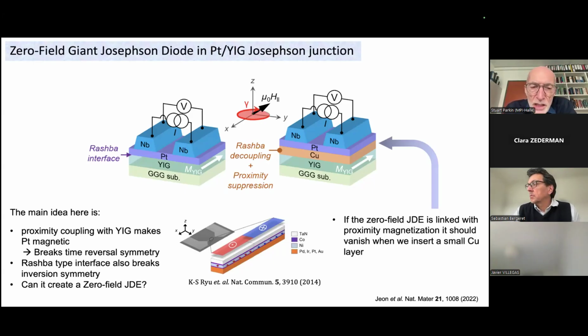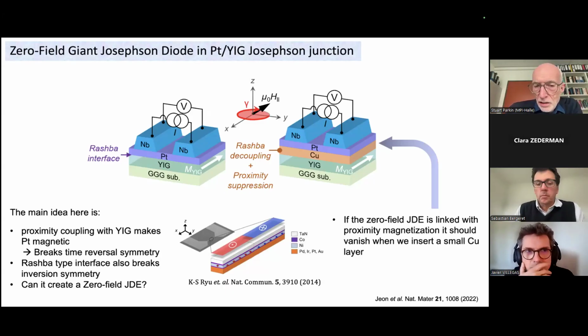In this case, we break time reversal symmetry in platinum by growing a platinum layer on a substrate which is insulating, but which is a ferrimagnet. This is a so-called YIG, a yttrium iron garnet film, and it has a net magnetization. It turns out you can magnetize that YIG in a direction with its magnetization perpendicular to the supercurrent direction, as shown in this cartoon by the white arrow. So the white arrow is the magnetization of YIG, and basically we apply a big magnetic field, go back to zero, and through the hysteretic effect, the YIG is magnetized in that direction in zero magnetic field.